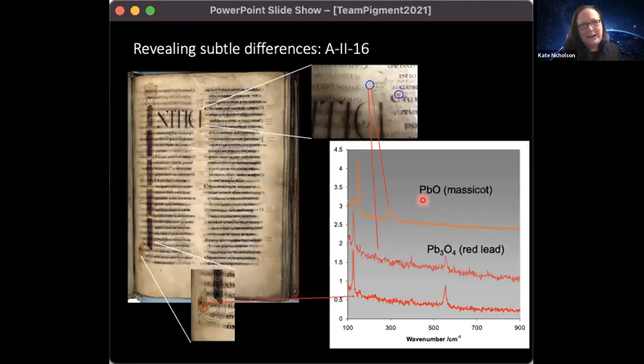So, how do we know that? Well, a later book in the collection, this one probably produced in York. And we look here and see, okay, there's some red lead on the page. Great. And we scour around, find another little bit of red lead and go, oh, that bit's got some massicot in. And then Richard breaks the bad news to us that that is actually a later addition, a later annotation put in by another hand several centuries after the book was produced. They weren't quite as good with their chemistry because it contains massicot. So we can see from this peak here. Red lead, no sign of it, massicot. So clearly standards were slipping.